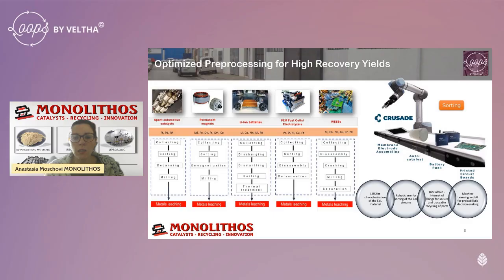So we have concluded that the streams should be separated, avoiding cross-contamination from one stream to the other, in order to have the purest possible streams and increase the efficiency of the recovery during the leaching process. Otherwise, by not having proper sorting of these streams, metals contaminate the streams between them, and finally we have a multi-metal component from which we cannot selectively extract the metals.